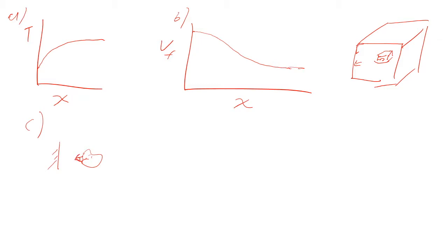To balance that out, the surface is actually compressed a little bit because of the viscous relaxation and the difference in free volume between the surface and the bulk. So you end up with a set of compressive stresses on the surface.